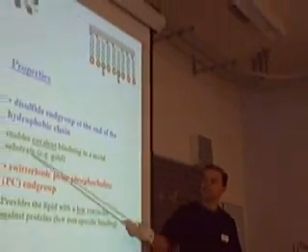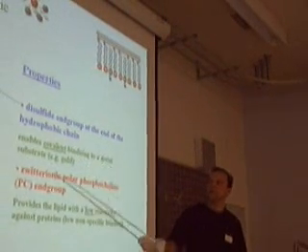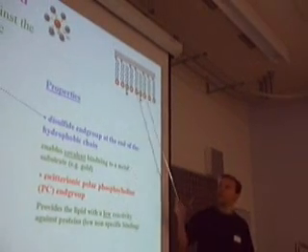But what we have then done is that we have, through synthesis, introduced a disulfide end group at the end of one of the hydrophobic chains. What that means and does, and gives as a function, is that it enables covalent binding to the metal substrate. In our case, we use gold. And in this way, we can get a very stable structure for practical applications.